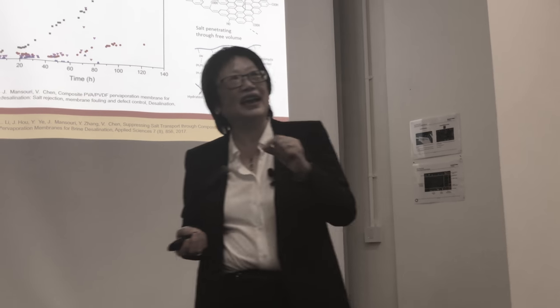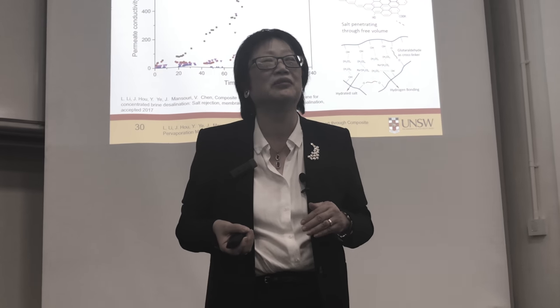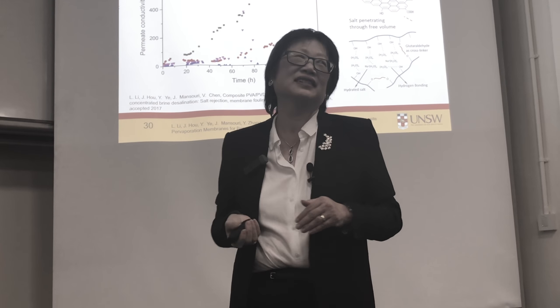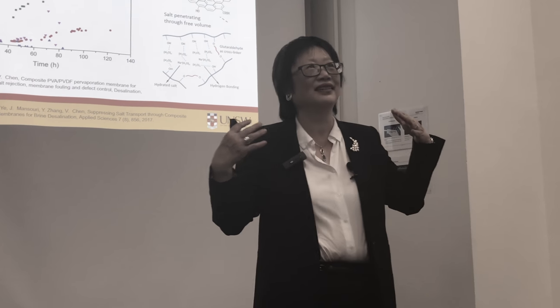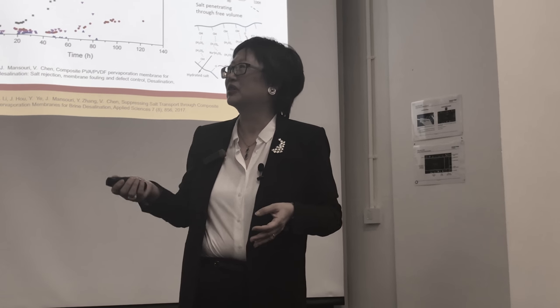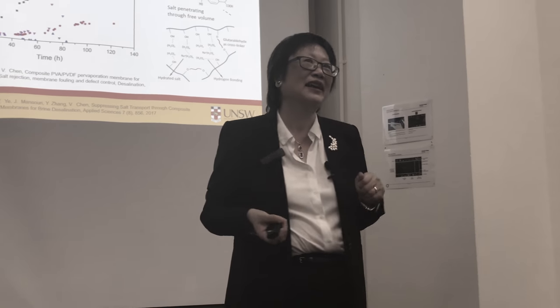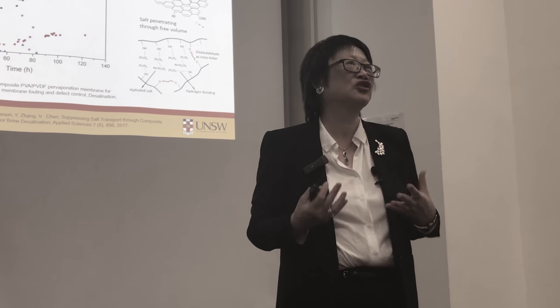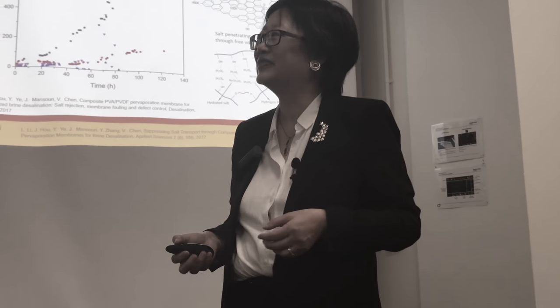When you add in these nanomaterials, it's not simply that they're used as porous fillers. They have some interaction with the polymers. Instead of cross-linking with longer reaction times, by putting in graphene oxide you're actually having hydrogen bonding and other interactions between the nanofillers and the polymer. And this is one of the themes I'll talk about: when we think about nanofillers, don't think of them as just putting in a porous material. They have quite strong interactions with the bulk polymer, and that has some consequences that perhaps were not foreseen.